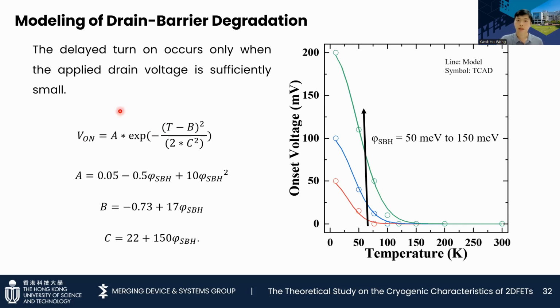Extensive device simulations were performed across a practical range. For example, temperature from 10 K to 300 K, source barrier height from 0 to 150 meV, with onset voltage value extracted through the output characteristics. Using Gaussian curve fitting, the onset voltage equation can be expressed as below, with A, B, C empirical fitting parameters.